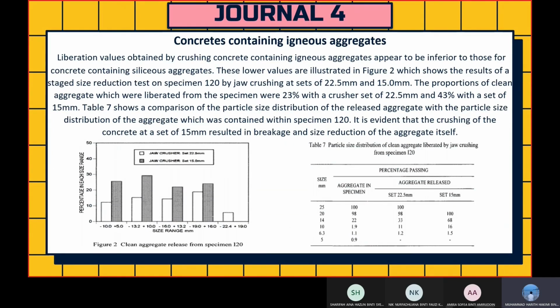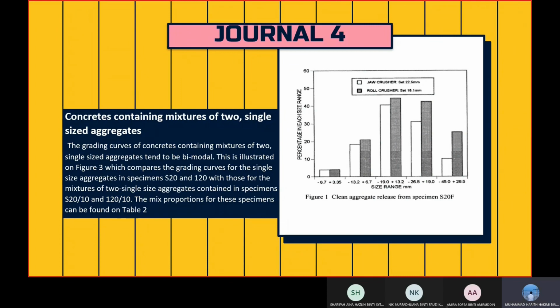The concrete containing igneous aggregate. Liberation values obtained by crushing concrete containing igneous aggregate appear to be inferior to those for concrete containing siliceous aggregate. These lower values are illustrated in figure 2. Table 7 shows a comparison of the particle size distribution of the released aggregate with the particle size distribution of the aggregate which was contained within specimen 120. It is evident that the crushing of the concrete at a set of 15mm resulted in breakage and size reduction of the aggregate itself.